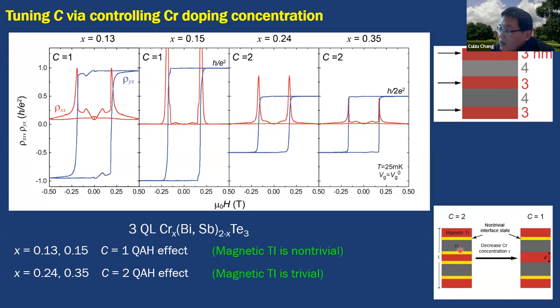If the doping level becomes higher, this becomes a normal insulator layer. There will be two quantum anomalous Hall layers here. It will form four non-trivial surface or interface states, and each is half quantized. So the total should be 2e squared over h. This is the C equals 2 quantum anomalous Hall layer.